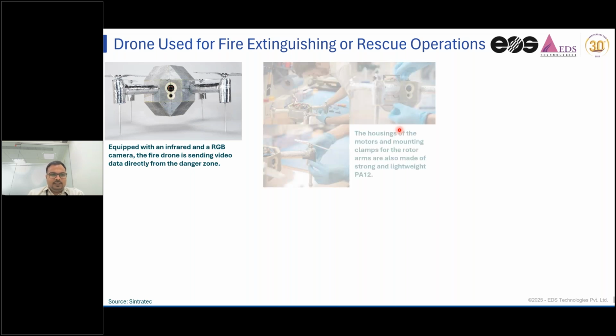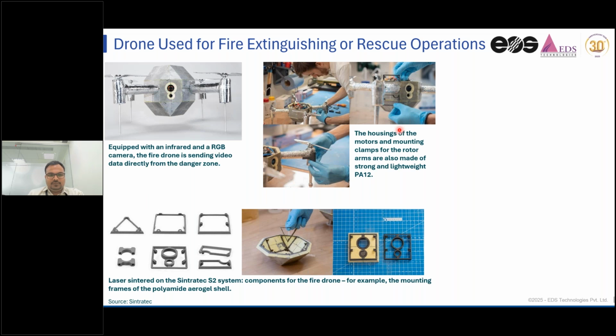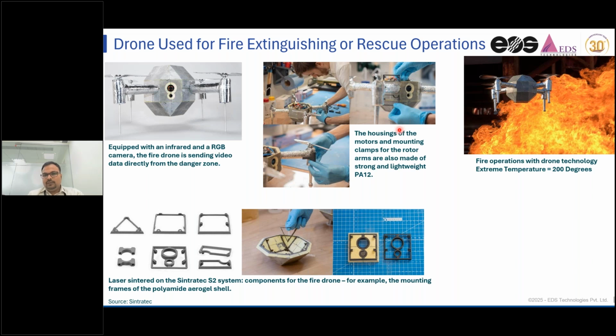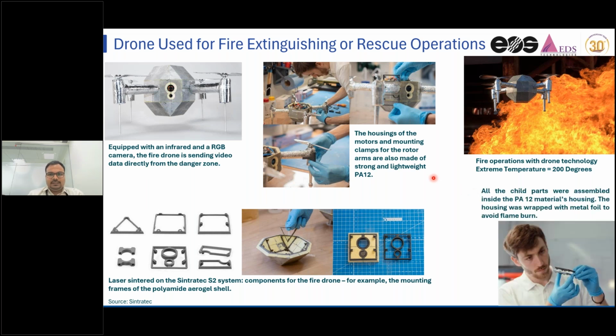So, what is the application with the flame retardant material? I have taken an example here where people have used polyamide 12 based material. This is not exactly a flame retardant material, but flame retardant material will perform better than this because this is the natural polyamide 12 material they have used, and they have literally put it at 200 degrees temperature, sent a drone to check how it is able to protect the internal electronics and internal components of the drone. So with the FR material, you can expect more protection than our normal polyamide 12 material.